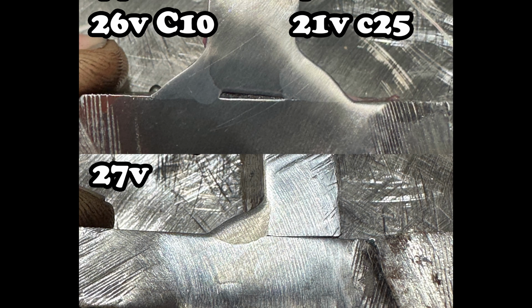I'd take the spray. With that said, one thing you guys got to remember is that spray is generally done in a flat position, and without pulse, you're not going to be doing too much uphill or overhead welding with it, versus the dual shield can be run in all positions fairly easily. It's actually easier to weld out of position with dual shield than normal short circuit MIG. So that will play a role in your ability to weld with these on a project, and that is a limitation of spray. And also, the dual shield has better sidewall fusion, and that could also be a huge benefit depending on what you're welding.